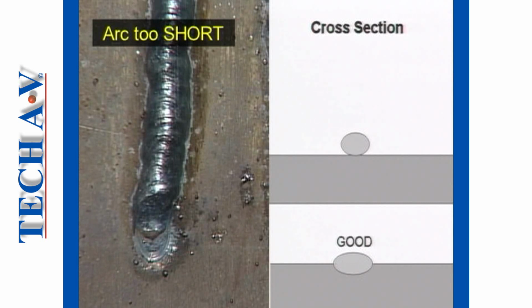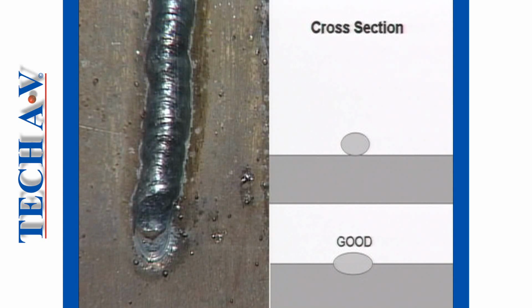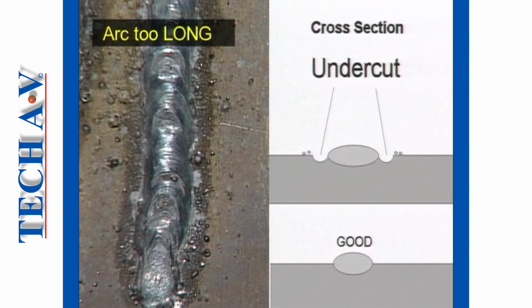This example is the result of holding an incorrect arc length. Here the arc length was too short, resulting in a narrow bead with little penetration. By contrast, an arc that is too long will produce a bead like this. Note the undercut at the edges of the bead, the untidiness of the ripples, and the excess of spatter.